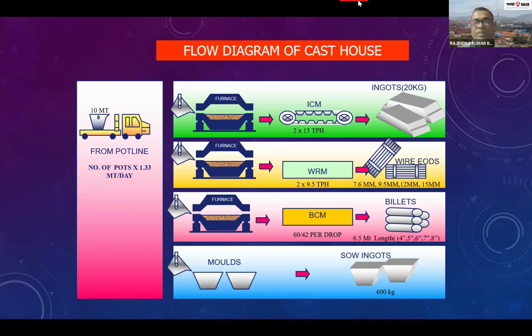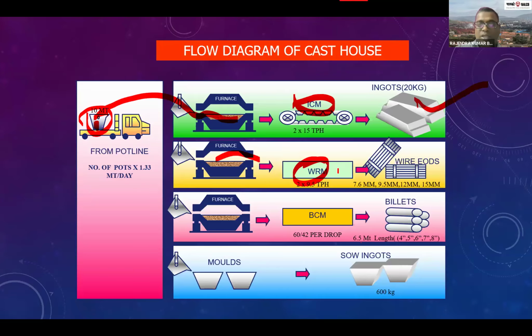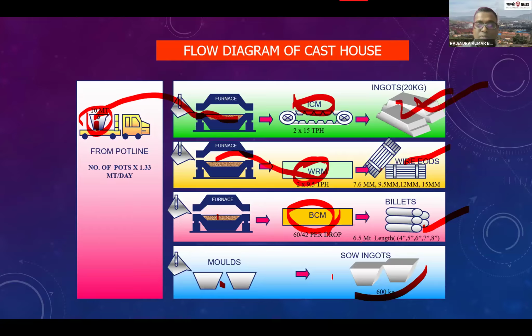Okay, flow diagram of the cast house. What are we getting from the pot line? The pot line material, we are getting 10 metric ton per pot and putting it in the furnace. Ingot, this is called ICM, ingot cast machine. These are the ingots we are getting here. This is a wire rod mill, where we are getting the wire rods. And the furnace has a billet casting machine. These are the billets. Each billet casting length is 6.5 meter, and this is 7.6 meter. Each ingot weight is 20 kg. Each sow ingot weight is 600 kg.